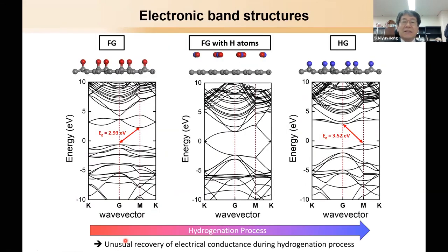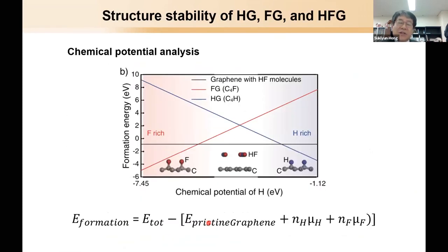substrate. And to understand this property, we did density functional calculations by considering the structures of the fluorinated graphene and hydrogenated graphene to find the hydrogenation process upon exposure to the hydrogen plasma. Also, the existence of the functionalized graphene can be explained by chemical potential analysis. And this is the formation energy as a function of the chemical potential of hydrogen. And now you can see the possible formation region of each functionalized graphene depends on the chemical potential